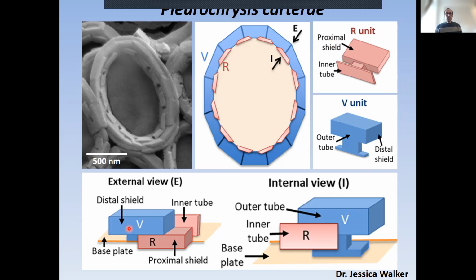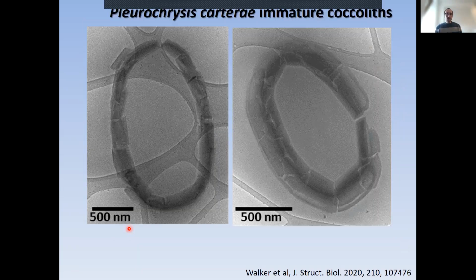What we did here was to extract coccoliths from the cells by bursting the cells open and just cryopreserving them and imaging again using cryo-TEM. This was the work of my former PhD student, Jessica Walker. And then what we did was, again, cryo-electron tomography to image them in 3D. So I have here two coccoliths at different stages. This is very much still forming. This is an almost mature state, but not quite there. They came from inside the cell.